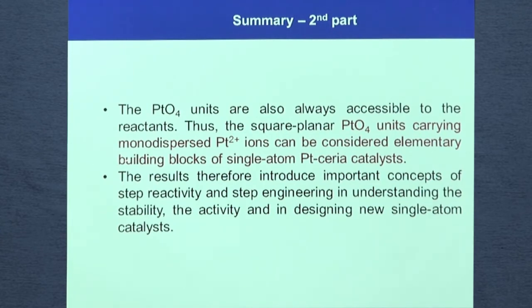So the summary of the second part: the PtO4 units are carrying monodispersed platinum 2+ ions, which can be considered as elementary building blocks of single atom platinum ceria catalyst. So this is what we are calling the single atom catalysis by platinum. The problem is, of course, that we don't really know very well what is the role of ceria here. We don't know that yet. If it's only stabilization of platinum, or if cerium oxide is activating hydrogen bonds, so it means splitting hydrogen 2 molecules into hydrogen atoms.